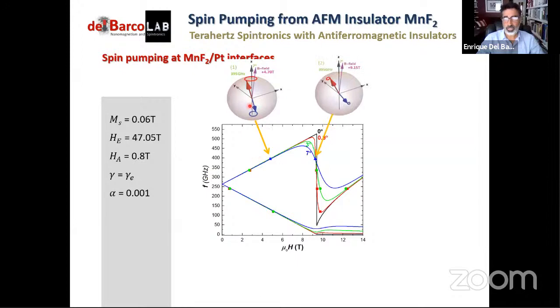Then we go into the spin flop transition and you see the axis of alignment for the Néel vector, the two sublattice magnetizations, starts tilting away from the magnetic field, but it's still a very circularly polarized mode. Then we go a little farther into the spin flop transition, and we get the sublattice magnetizations basically perpendicular to the applied field, as you go up above the spin flop transition. But still, the system maintains a pretty good circular polarization.